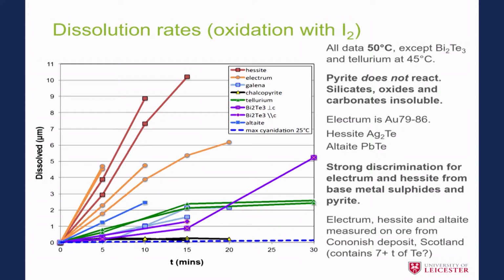Okay, so at the bottom, in dashed blue here, we have the cyanidation rate of gold at 25 degrees C. Now, obviously, our data are at 50 degrees C. It's not a direct comparison. Our rates would be slower at 25 degrees C, but our rates are much, much faster here. So we can easily dissolve gold as electrum, but we can also dissolve hessite. So if you had a deposit which had both of those in, and in fact the samples actually came from our little gold deposit in Scotland,